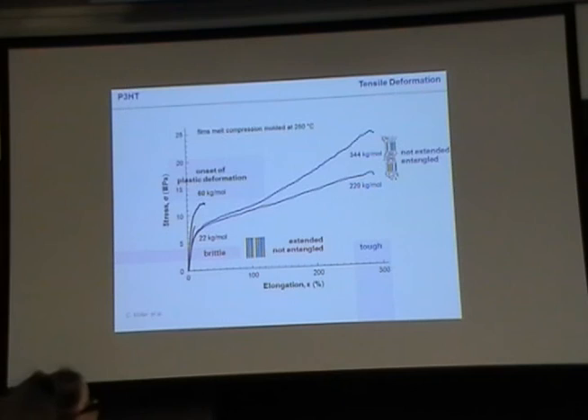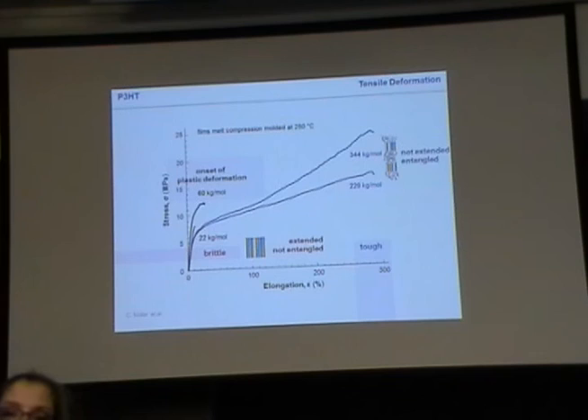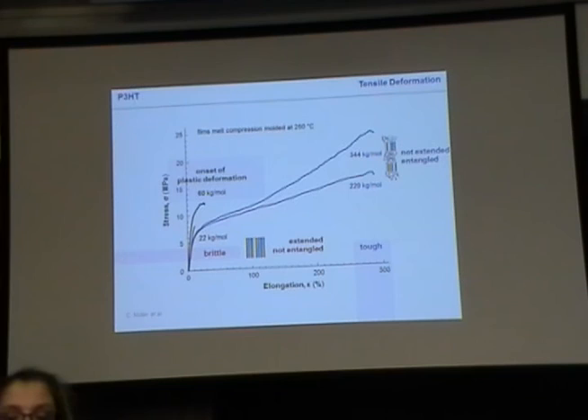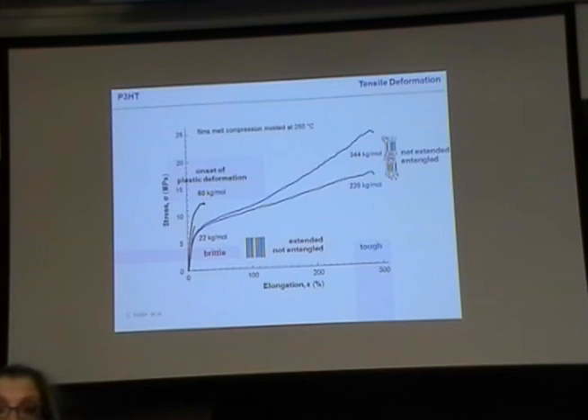Question: Does this orientation affect the electrical property? Answer: People have tried to make transistors with oriented polymers. Sometimes very large anisotropies were found — sometimes ten to a hundred times — actually including me. However, often you had to do something to orient the material, like use an alignment layer. So sometimes the anisotropy you saw, I don't believe came from the orientation but because you had more inhomogeneities in one direction due to the alignment layer. If you look at recent single crystal work, I think the anisotropy eventually is not that large — other aspects are much more dominant.